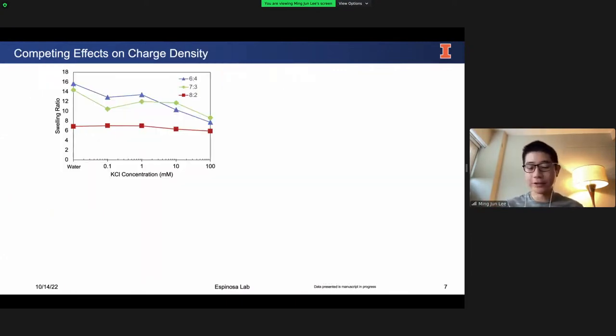Now I'd like to talk about the charge screening effects. And the first figure I'm showing is the swelling ratio against potassium chloride salt concentration. Swelling ratio is taking the weight of a wet hydrogel divided by its dry weight when all the water has been removed. So this is a measure that tells us how much the hydrogel is swollen, like in terms of volume.